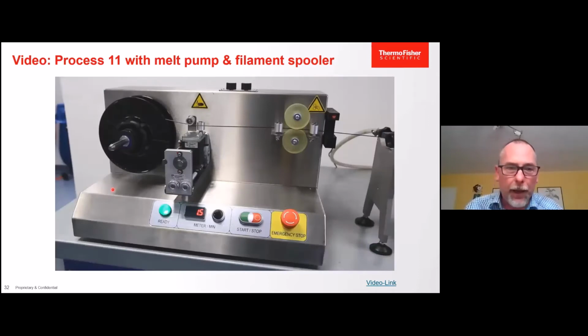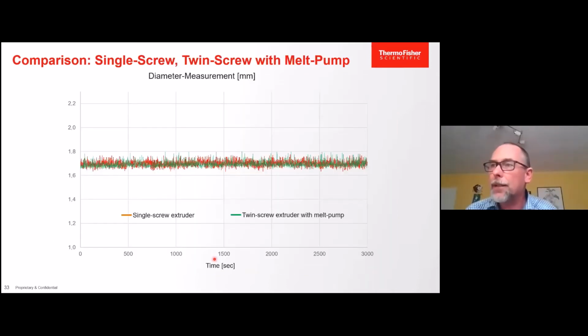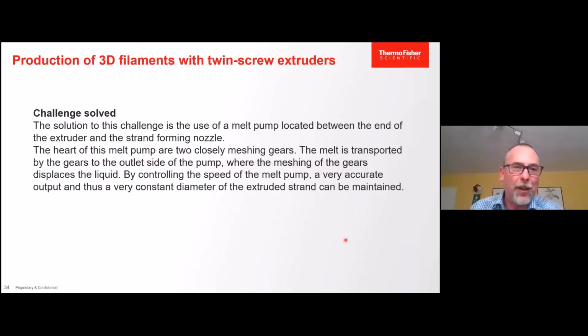We compared actually the results of a twin screw extruder, green line, with a single screw extruder, orange line, and a twin screw extruder with a melt pump, and it's in the same range. So we can say here we have challenged, solved. We can create those strands by using a gear pump, and for you important, we can now design your own material. If there is a compound not available in a catalog as a ready strand, we can design it. We can make those types of compounds and go to a further process.